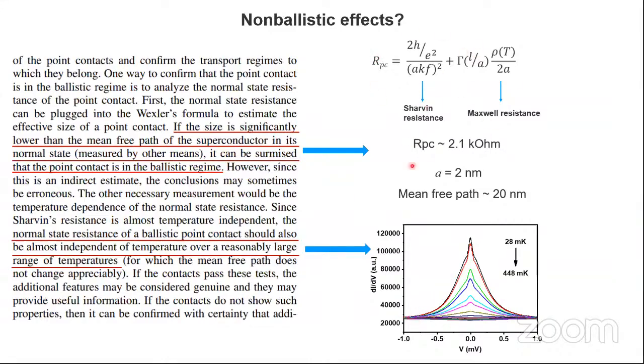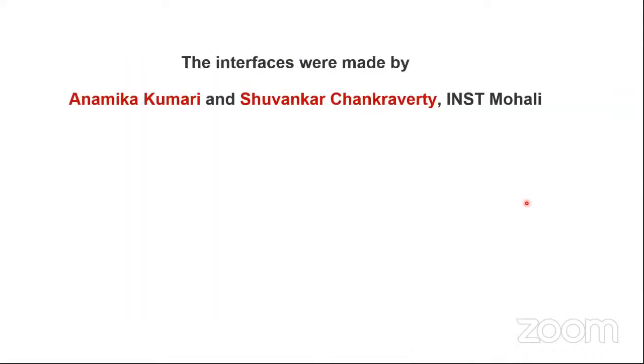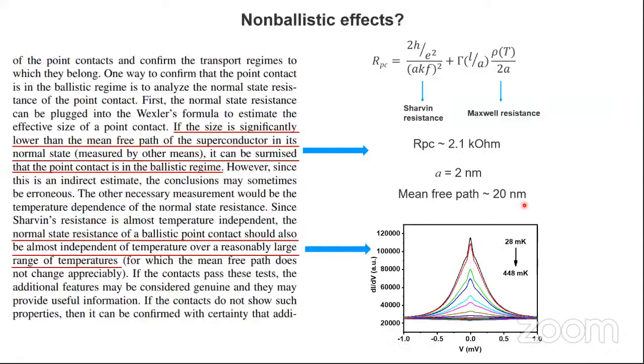And from the normal state resistance, we found the contact diameter, which is much smaller than the mean free path that is known for these 2DEGs. Therefore, we can conclude that probably we are looking at unconventional superconductivity here.